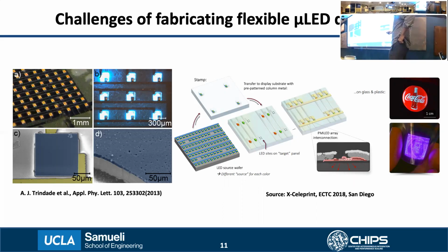So in this chart, I basically provided some samples of what people have done in this particular field. On the left side, this is an example from literature where this group had printed 200 by 200 micron square LEDs on a PET substrate and then interconnected them using thin film evaporated metallization. And on the right side here, this is an example from industry, a company called X-Celeprint, that uses a viscoelastic stamping technique to pick up and then assemble the LEDs on a PET substrate, where they have interconnected them either by using evaporation or by using electroplated interconnects.